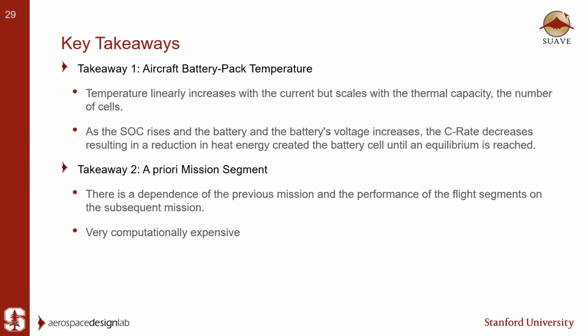From the previous slide, we get 2 main takeaways. First, the results from battery pack modeling suggest that the pack temperature linearly increases with the supplied current, but scales with thermal capacity. Using a similar submodule, module, and pack configuration of the X-57, it was discovered that each cell was exposed to large currents during takeoff, the most power-intensive phase of flight. The thermal model predicted a maximum temperature of 45 degrees Celsius, which occurred at the top of climb.